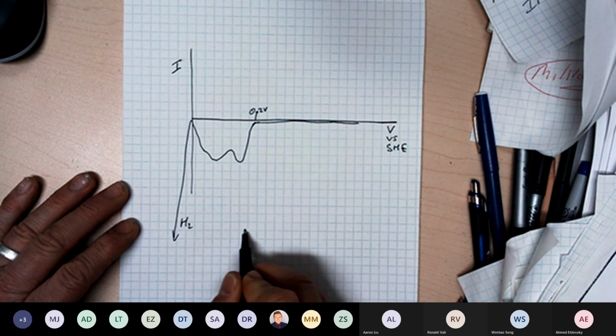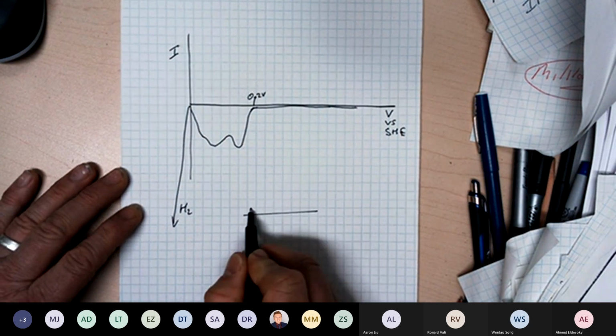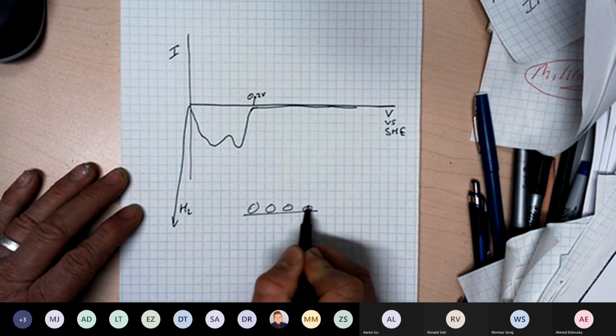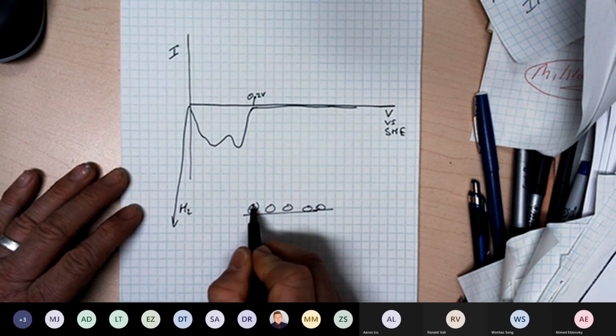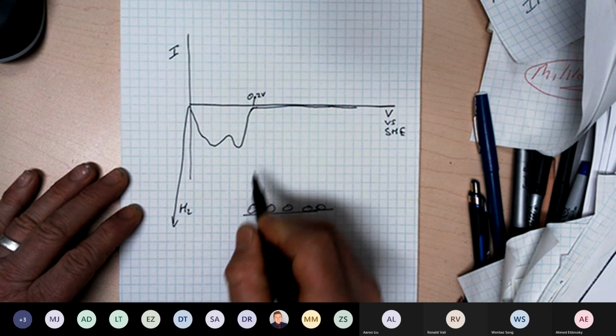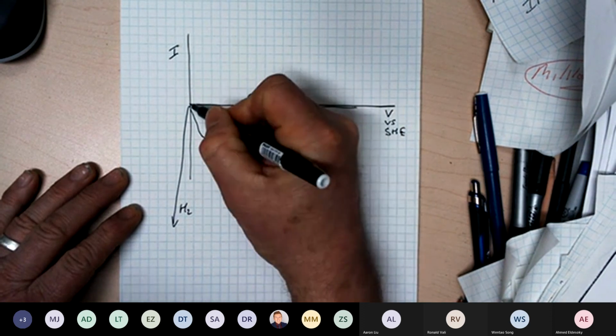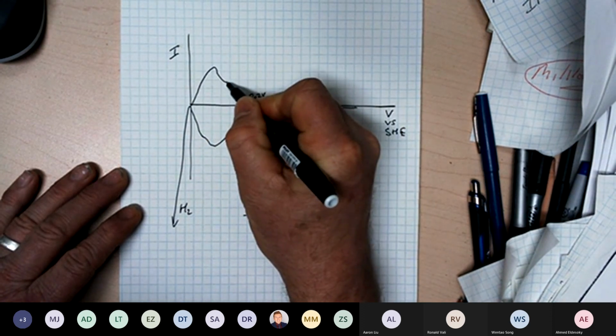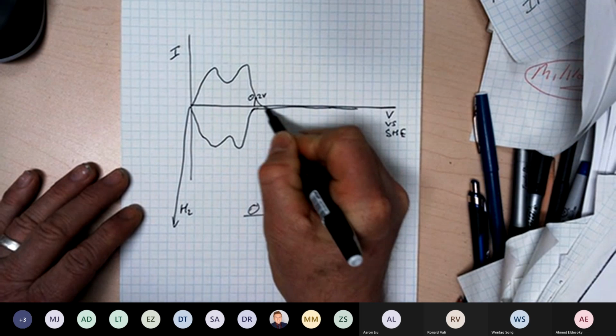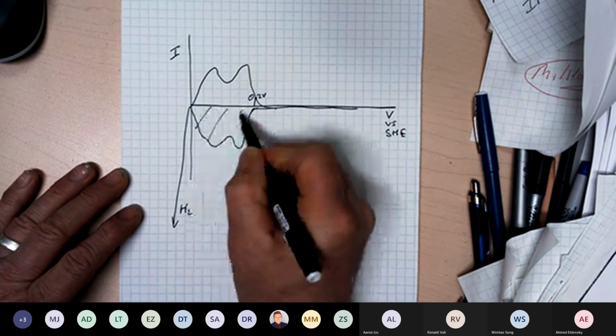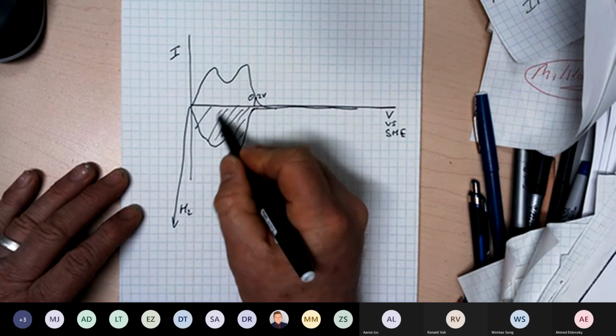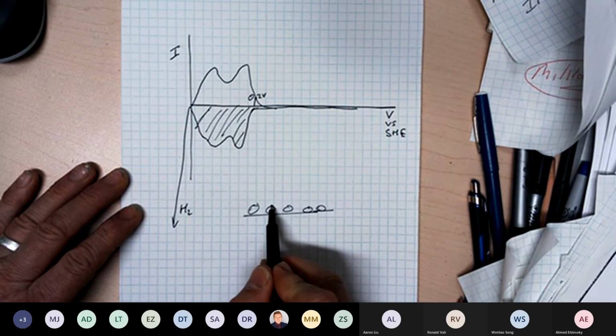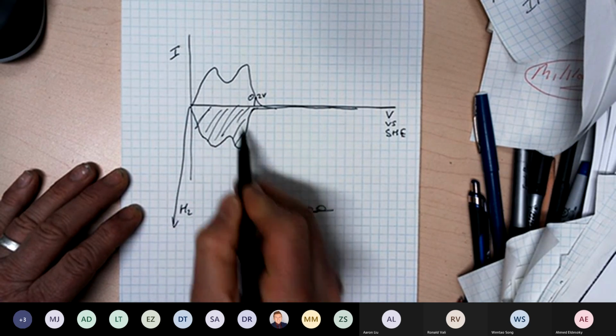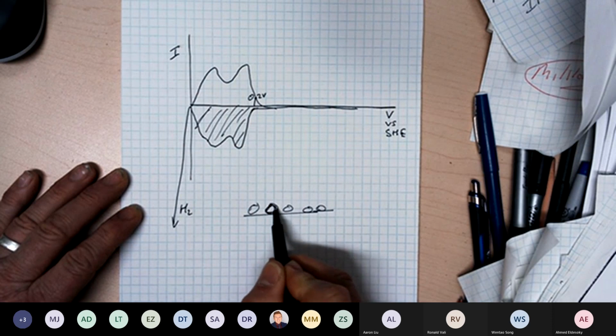So what happens is the platinum surface gets covered with hydrogen. At first it goes down as atoms, and then it becomes molecules. And then when you go in the other direction, it strips off. And the area of this curve is proportional to the surface area of the platinum. The area under this curve is proportional to the surface area of the platinum.